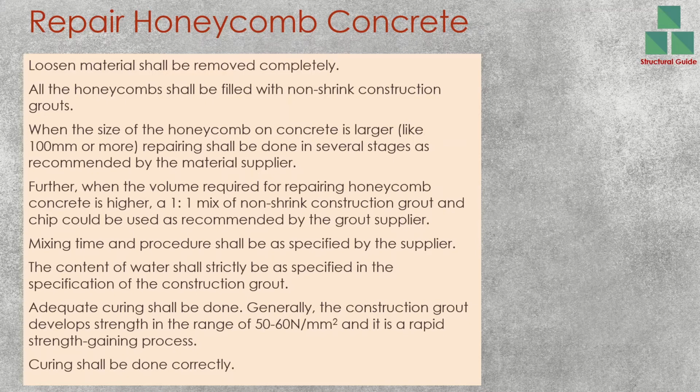Non-shrink grout gains a strength of about 50 to 60 newtons per square millimeter. It is generally high strength concrete, and it also gains strength very fast. Not like cement, it gains strength in a very quick time. Therefore, you have to do the curing also. Even after placing the concrete, you have to do the curing. That you have to keep in mind. Continuous curing shall be done because in a short time period it gains the strength.